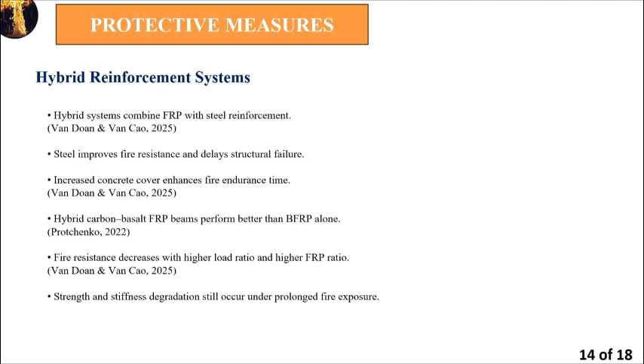So this we will have some kind of improvement. Researchers also show that hybrid beams generally perform better in fire conditions compared to beams reinforced only with FRP. They have improved fire resistance times and better residual capacity after cooling. However, it is also important to note that strength and stiffness degradation still occur. If the fire duration is long or the load level is high, the structural performance will still decrease significantly. So the final point is that hybrid reinforcement systems improve fire performance compared to pure FRP systems, but they do not completely eliminate the problem of thermal degradation.